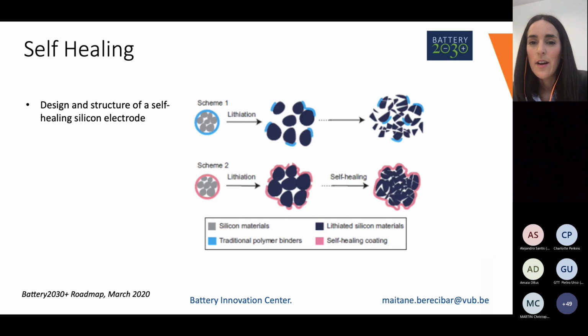Therefore, it's very interesting. However, with silicon, we have a problem, because through the cycles of charging, discharging, lithiating, delithiating, the silicon expands. That's what we see in the figure above. So after many times of charging and discharging, the silicon can reach a breaking point. And there, of course, we are losing the property that silicon is bringing to batteries.